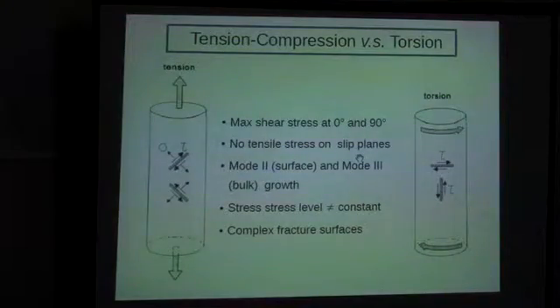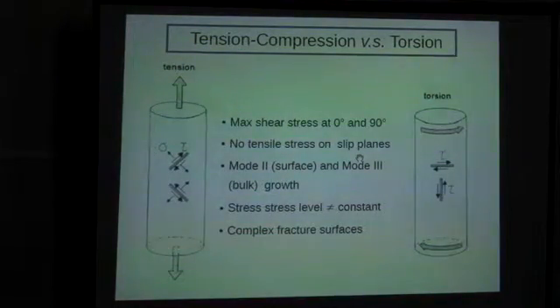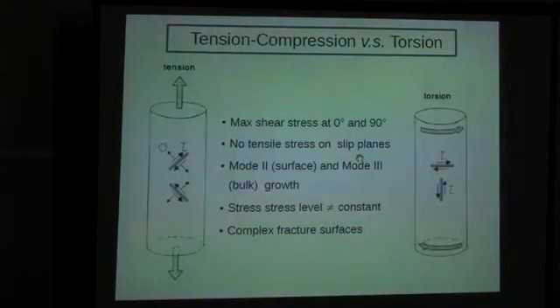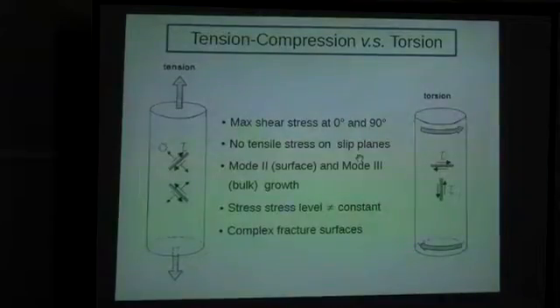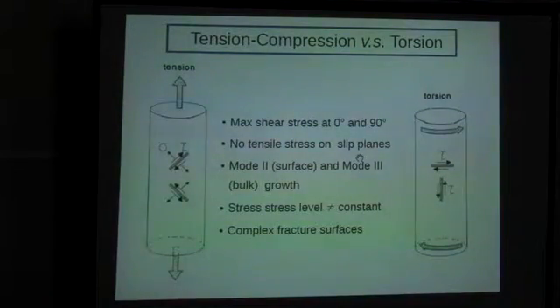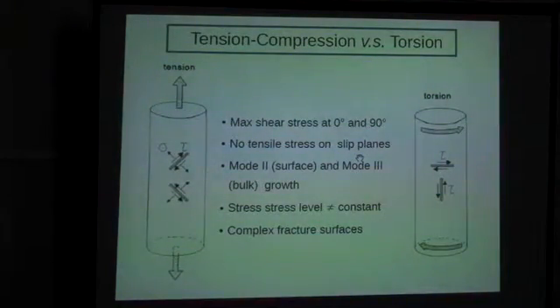There are many differences between torsion and tension-compression. I have highlighted some important ones here: maximum shear stress is at 0 and 90 degrees and not 45 degrees, and there is no tensile stress on the slip planes, which makes crack initiation sometimes problematic. At the surface, the cracks are loaded in mode 2, whereas it's mode 3 in the bulk, and the stress level is not constant across the section.